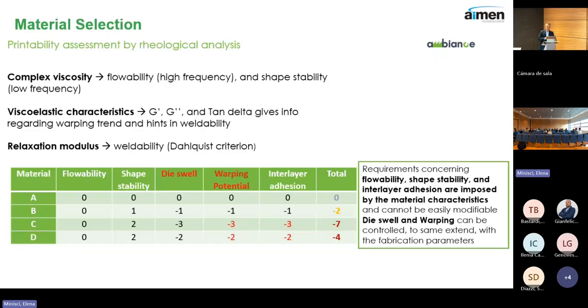Something important that I should mention here is that among all those characteristics that I'm showing in the table, so flowability, shape stability, warping, and interlayer adhesion, the flowability, the shape stability, and the interlayer adhesion depend mostly on the material. So this is not something that you can modify easily with the processing conditions. You should have a clear picture of those parameters in the material to know its potential for 3D printing. In the case of warping, the situation is slightly different. Of course, warping depends a lot on the nature of the material, but this is something that you can play with just by modifying the fabrication conditions.